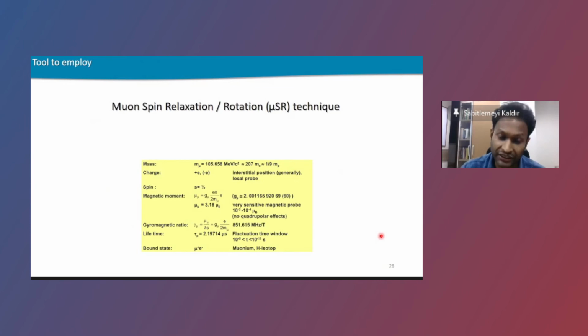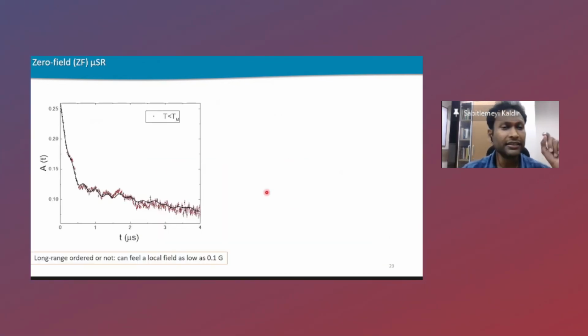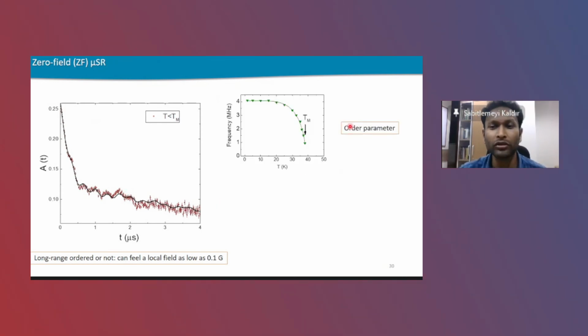And this precession frequency is nothing but proportional to the order parameter. Okay, so now this is the typical μSR data, the asymmetry as a function of time. You see that there are nice oscillations. The data has been taken below the ordering temperature. If you take the Fourier transformation of it, it is going to give you the idea about the local magnetic field. This is nothing but the precession frequency. So if you track that, you will be able to figure out the order parameter.